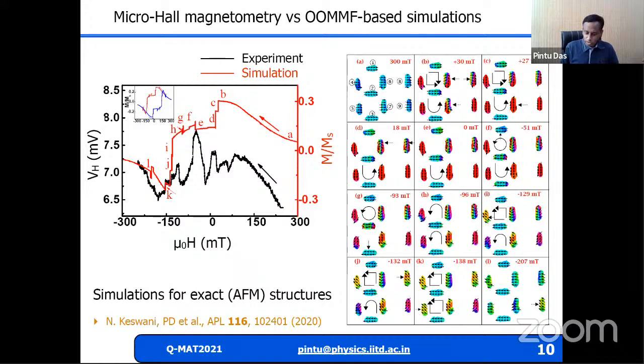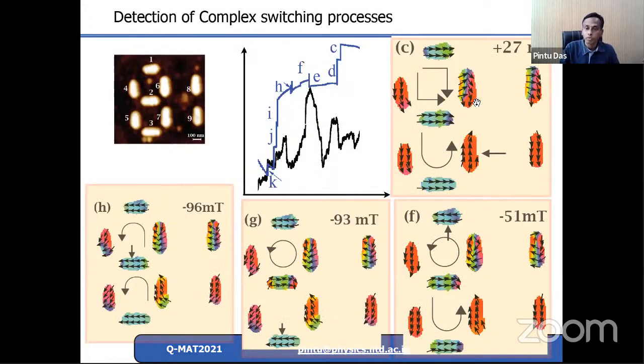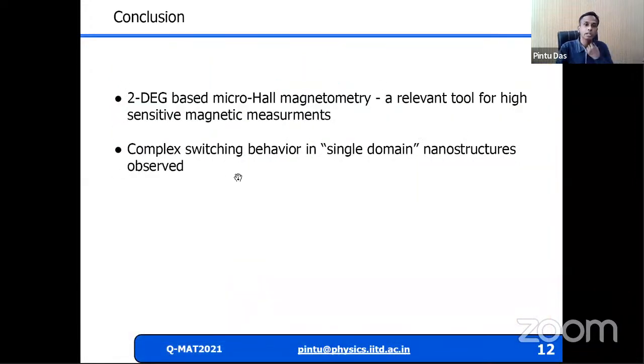So I'm not going too much into details. This is just to tell you that these very minor features that are observed in our measurements are related to some kind of magnetic behavior of the nanomagnets during switching. Okay, so these are a few examples at different magnetic fields, where you see vortex structures, and corresponding to these, there are features in the simulation results as well as the experimental result. So in brief, this two-dimensional electron gas based micro-Hall magnetometry is a relevant tool for very highly sensitive magnetic measurements. And we have used this technique to study complex switching behavior in single domain nanostructures.